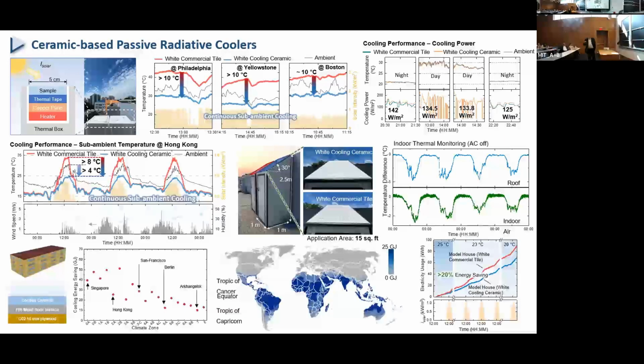We also went to different cities to study the effect of various climate conditions on the cooling. No matter which city, including Boston, where we did it two years ago, we can achieve sub-ambient cooling. Then we built two separate model houses on the rooftop, about 15 square feet each. Here we have more than 200 pieces of small ceramic tiles made by our lab, compared to the commercial white tiles. By naked eye, there's no difference in appearance.